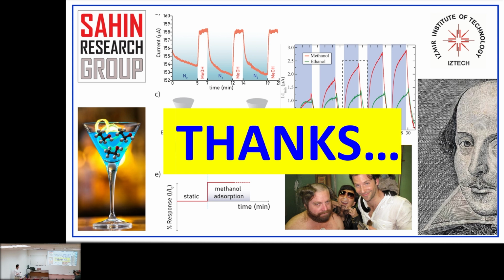It is interesting that in the example of methanol and ethanol, which is for me surprising and very interesting, it's really possible to eliminate all the methanol and ethanol as soon as you stop the input, because the conductivity goes down to the initial state. So it is surprising that everything is evaporating. In spite of the strong coupling of the surface with methanol, it is eliminated as soon as you eliminate the input of methanol. They have van der Waals type bonding with the surface. This is why when you send nitrogen gas, you can clean. Since there is no chemical bonding with the surface, we are able to clean. It's possible to clean only with nitrogen, and very rapidly, in several seconds. They go away.